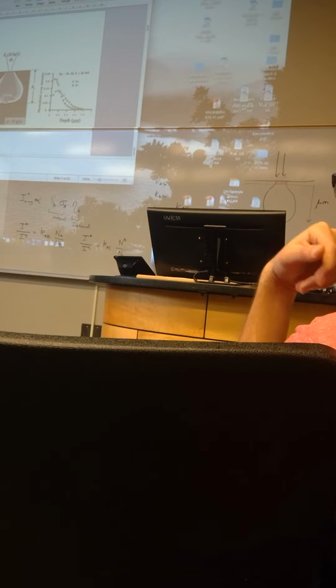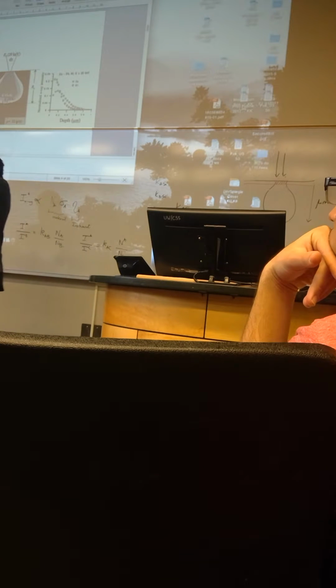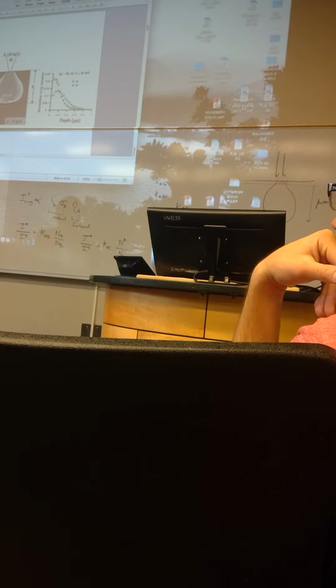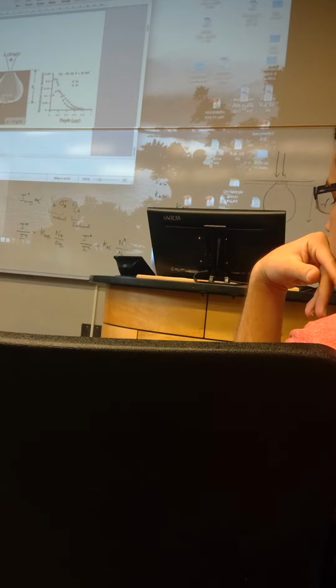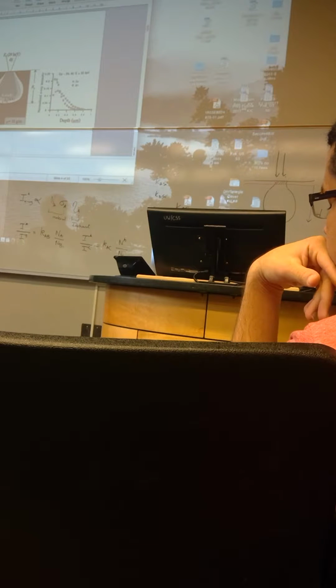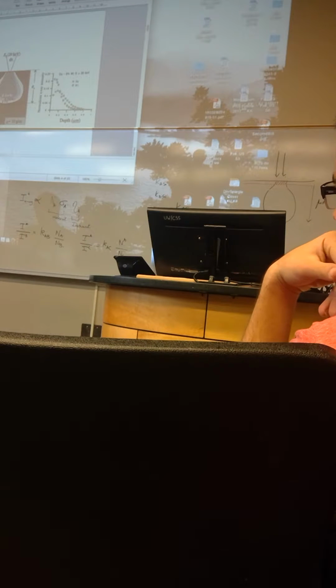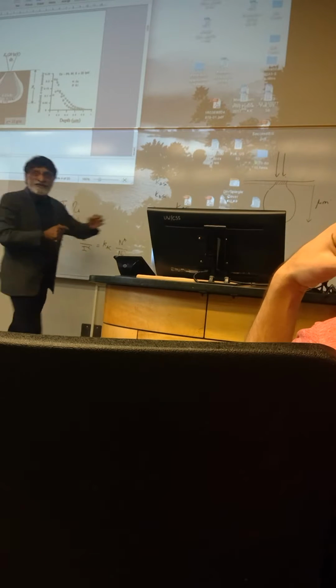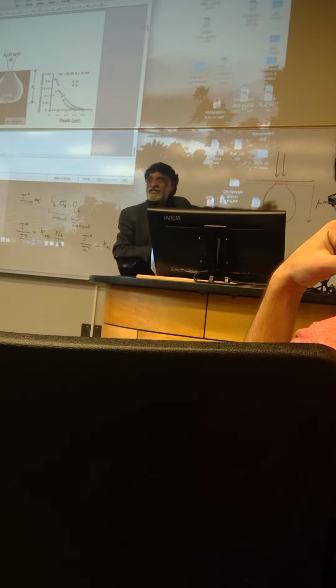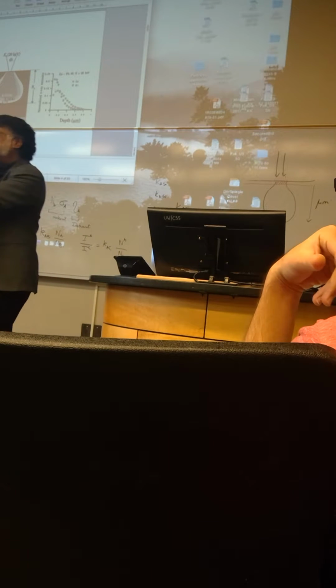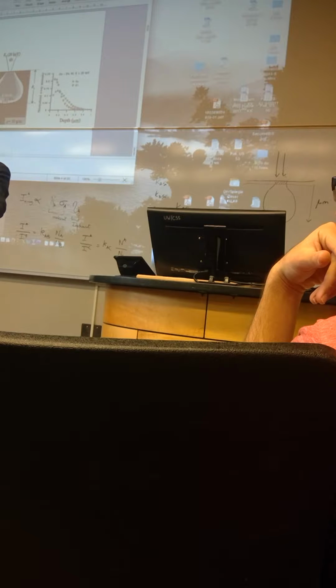So in some way, if you make a very thin foil and analyze in a TEM, your analysis will be far more accurate than what you would do with an SEM. Is this point clear? The only problem with that is you have to make a thin foil, whereas with an SEM you can just put your bulk sample in and do your analysis.